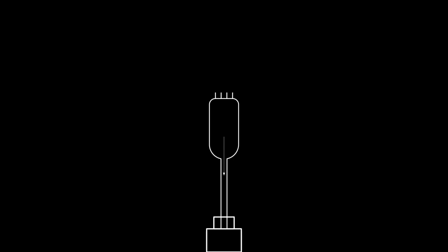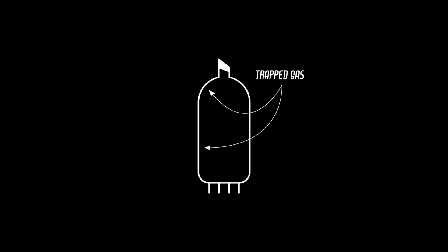Once you've sucked all of the gas molecules out of your tube and you close it off, there are still going to be some molecules which are left adsorbed onto the surface of the active elements or the glass envelope itself, and those molecules will escape into the atmosphere of the tube over time as the tube heats up and is used. The pressure inside the tube can actually increase to the point where it stops working correctly. Plus, if these gas molecules are something like oxygen, they can damage the active elements in the tube by oxidizing them, especially elements that get hot, like filaments.